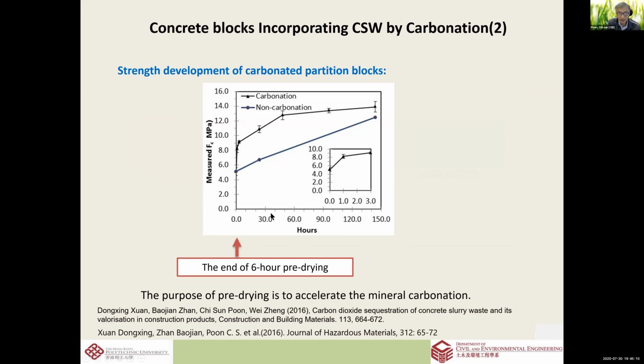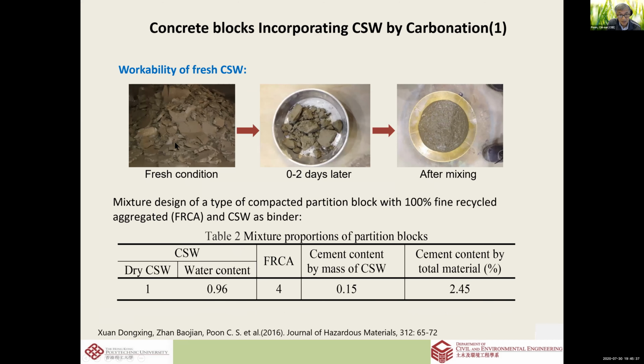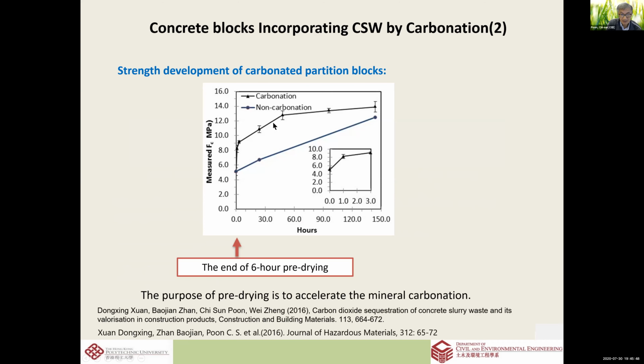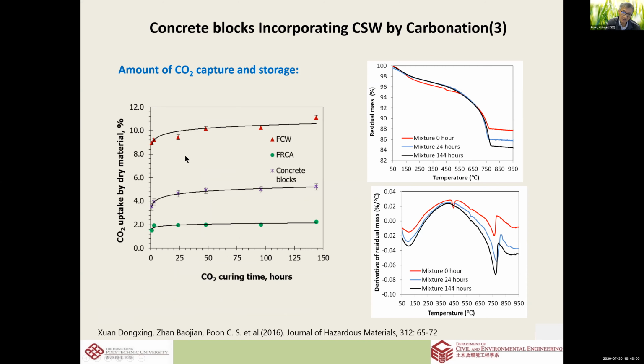When you mix it with recycled material like recycled fine aggregate to produce a block, and then carbonate it, we manage to produce strength after a few hours that is already good enough for shipment, rather than waiting for a few days. In this particular mix, we are using the recycled concrete slurry waste as the binder, and recycled fine aggregate as the aggregate, and the carbonation reaction produces very fast strength, so within 6 hours it can be delivered.